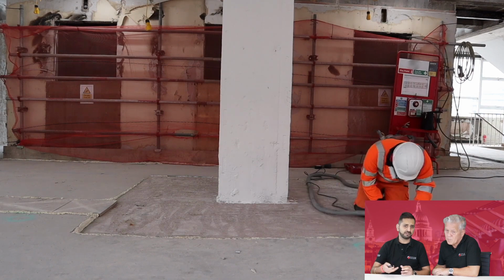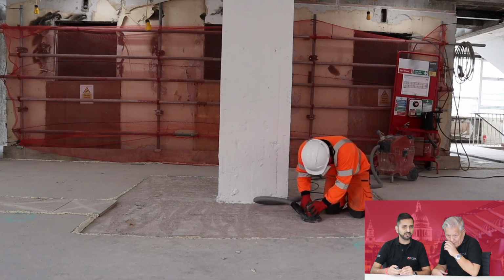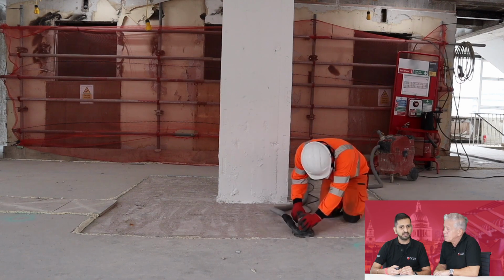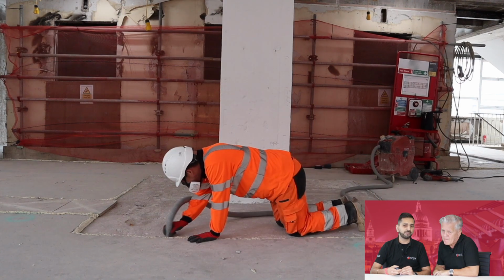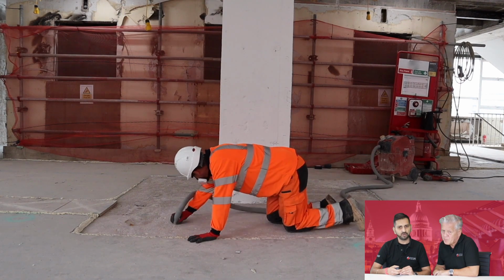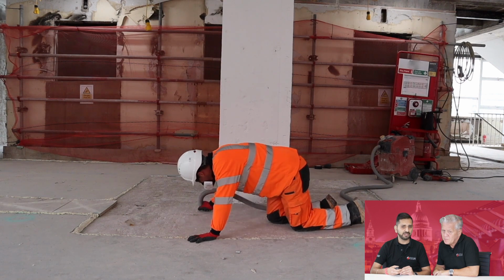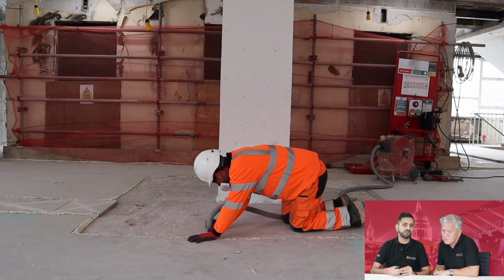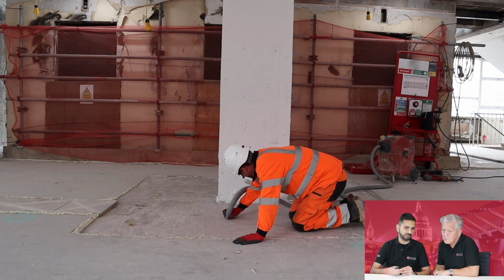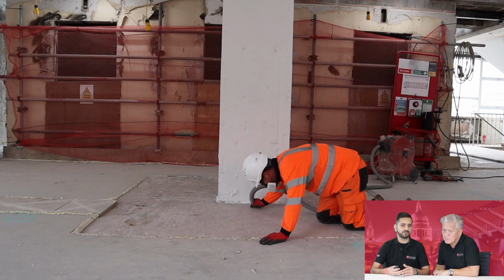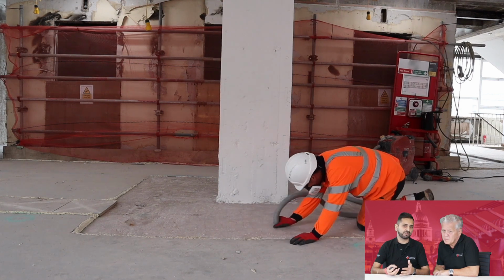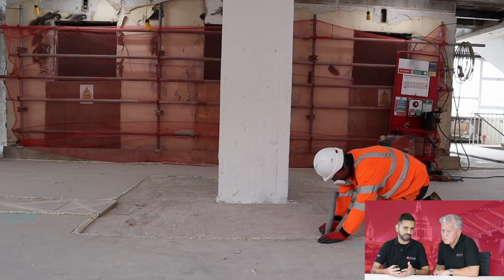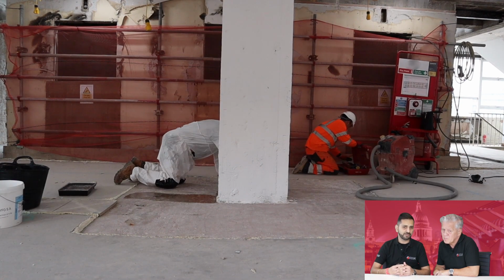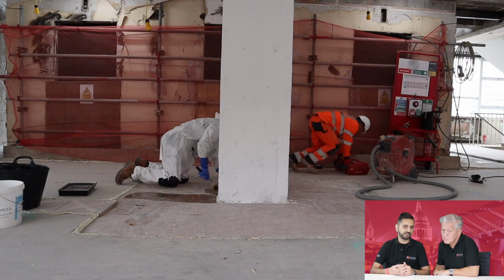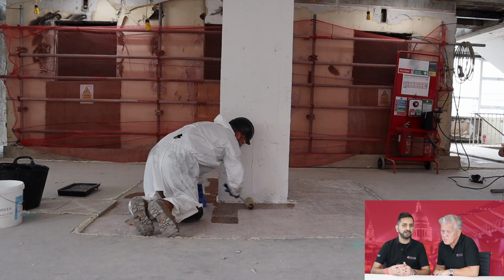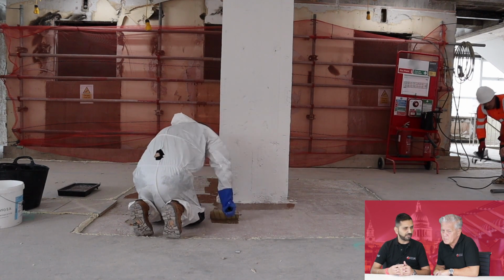There are different stages of application. The first thing is surface preparation, which in a building environment is mostly done using diamond grinding, followed by cleaning. You need to clean the area so it becomes dust free. Then you do priming, which is usually done using pure epoxy. The reason for using pure epoxy is that it can soak into the concrete and give you a proper key and bond. Then you apply the first coat of thickened epoxy, which is the white colored epoxy you've seen there, and then they unroll the first layer of carbon fiber.